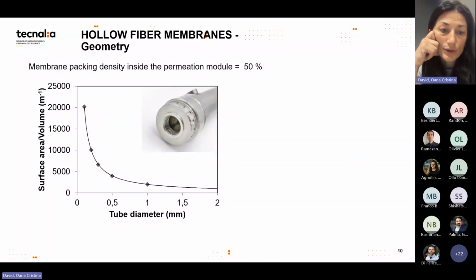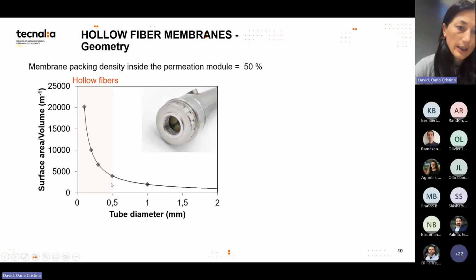So the motivation to go to such small fibers is related to how much membrane area we can pack inside a separation module. And here it's a simple calculation. We have the diameter of the hollow fiber. We consider that the surface area on the outside is where the membrane is. And we also consider that we can pack about 50% of the inner volume with these fibers. So we made a simple calculation, and we can see that when the tubes have an outer diameter lower than 0.5, we have an exponential increase in the packing density.